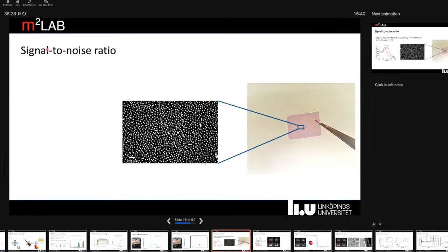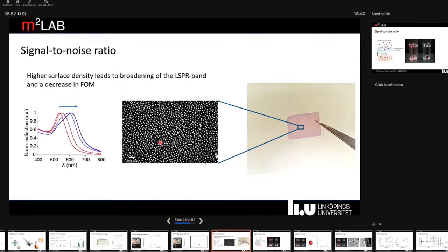This is a photograph of a glass substrate that has been functionalized with gold nanoparticles. And you can see this faint pink color comes from the particles. And here we actually have a fairly high density of particles. You can, of course, squeeze in more particles. It's definitely possible. But then what starts to happen is that we get a broadening of the plasmon band and a redshift, and that has a negative impact on our figure of merit and the sensing performance. So we can't really improve the signal intensity by just squeezing in more particles here.